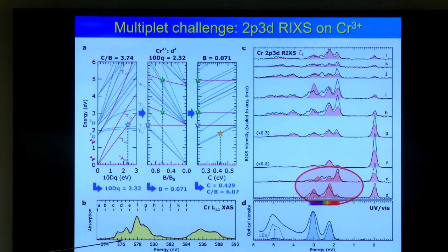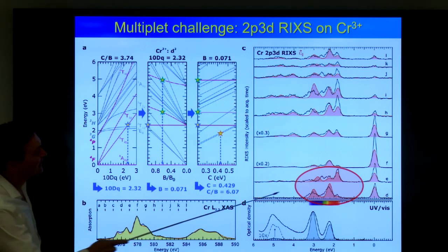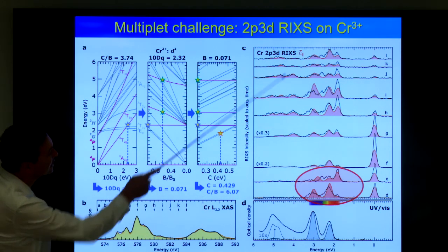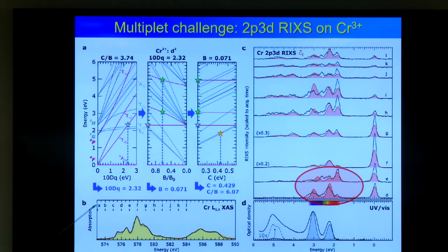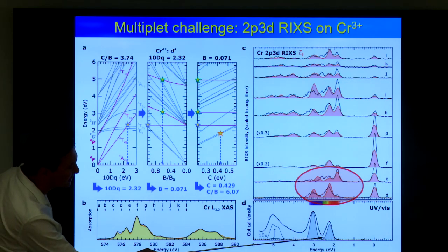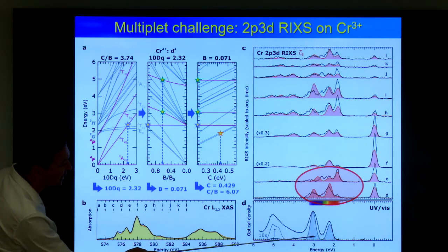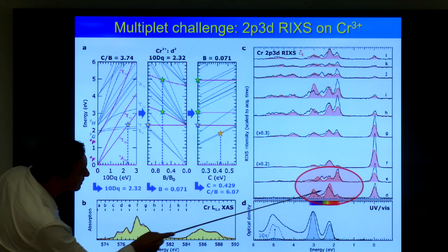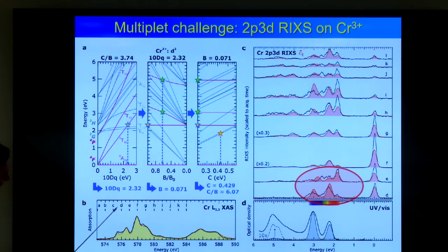It's perfect on this. These are the RIXS spectra excited at these arrows. So we were not very intelligent. We just took 1 electron volt steps in the ADRESS beamline. And this is the optical spectrum. So the optical spectrum has dipole allowed transitions, and you can see that they come back at excitation D. So if you excite there, you get the spin allowed transition.